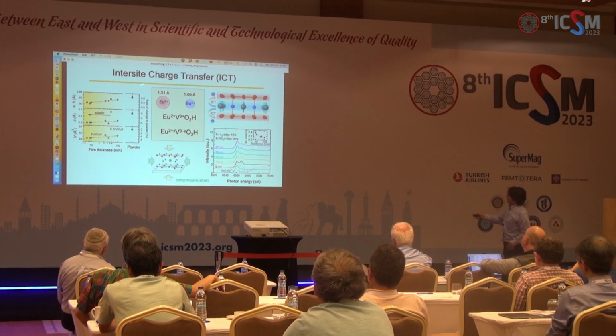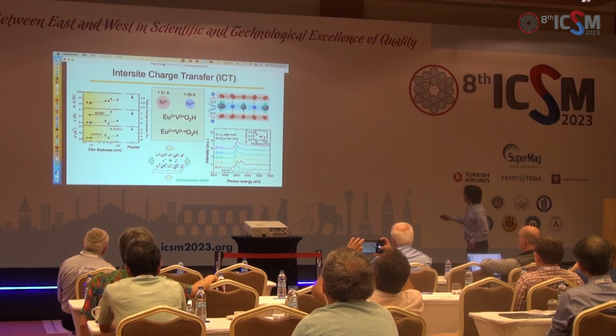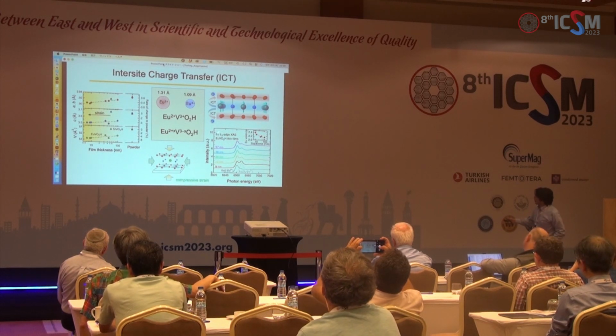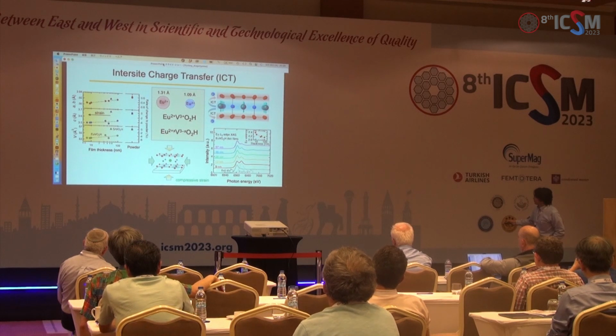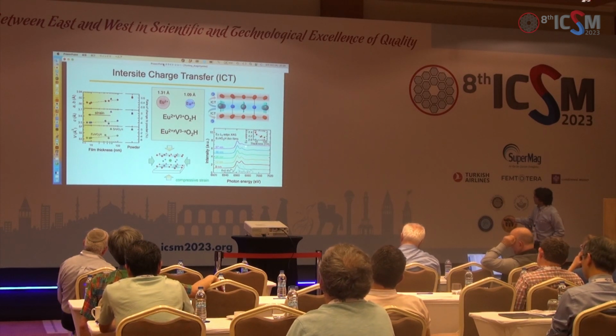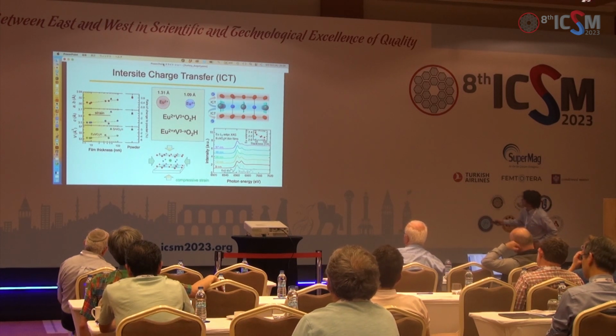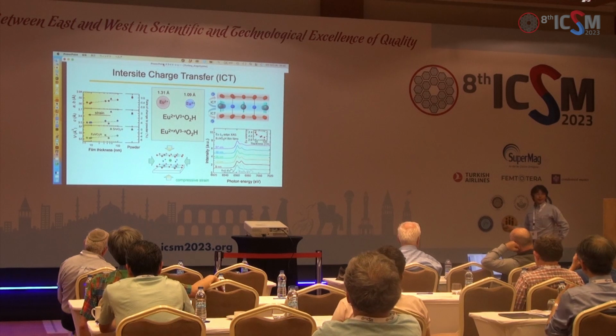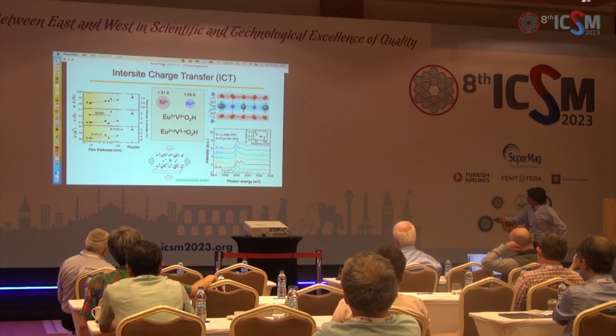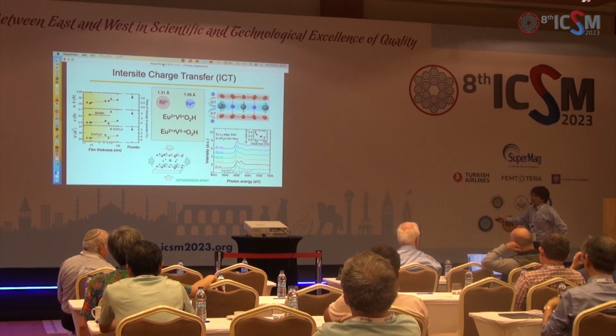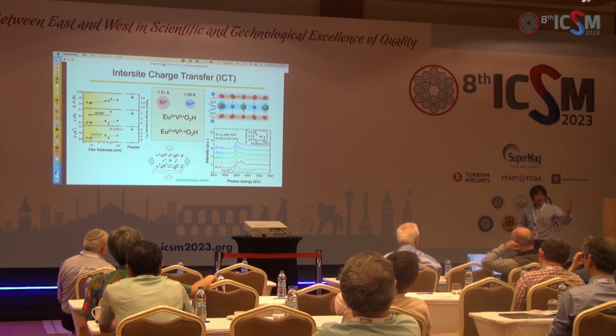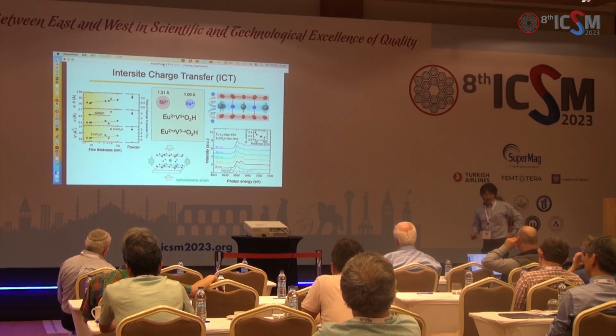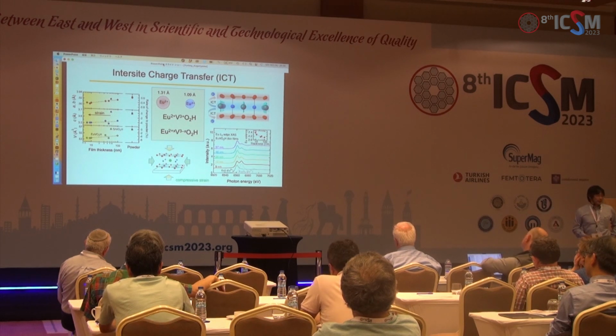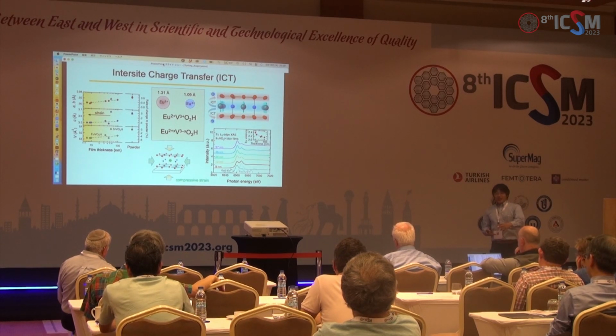But actually this speculation was supported by this X-ray absorption spectrum. This is the spectrum depending on the thickness. Okay. So you see that this right-hand side corresponds to the 3+ state. As you decrease the thickness, this peak intensity increases. So this means that the thinner film has more 3+ ions. This charge transfer, the charge transfer means the charge transfer from Eu to vanadium. So now vanadium is reduced and Eu is oxidized.